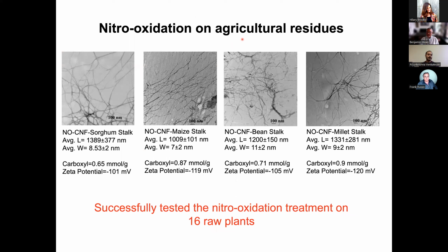We have tested 16 different raw agricultural residues. This just shows you nitro-oxidized CNF cellulose nanofibers from sorghum, from maize, from beanstalk, from millet. The length is usually pretty long, and the width is pretty small. Of course, once you use a more harsh condition, the width can be even thinner, and the length will also degrade. But we're mostly interested in this zeta potential, which is negatively charged, because negatively charged materials are, number one, stable in suspension. Number two, they can be used immediately to remove positively charged contaminants.